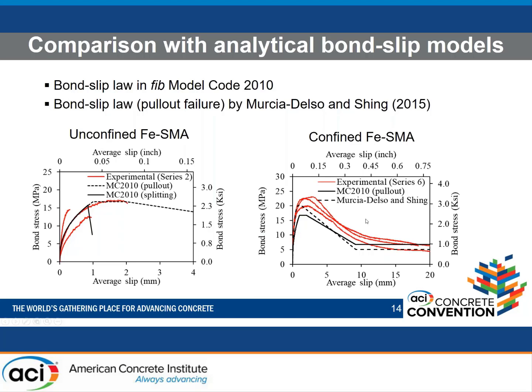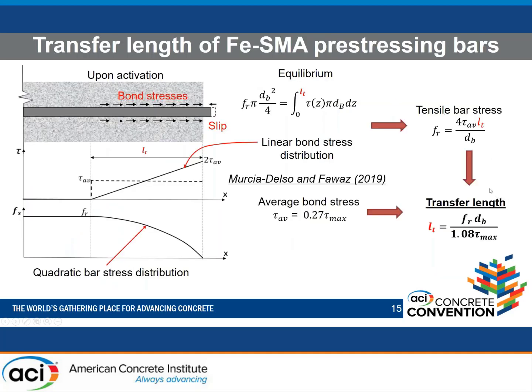And for the confined case, we see that SMA bars are giving higher bond strengths as compared to the models. The Murcia-Delso and Shing model is giving closer results in terms of bond strengths, but in terms of the shape with the plateau of FIB, it's giving a better prediction. For the residual, we have very good predictions for both models. We're very close to the experimental results.